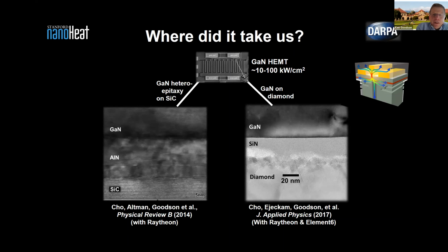It's basically a power transistor that's used for radar applications, a lot in flight, aircraft, and various things. And it is one of the great power density challenges of our day, because it's delivering millimeter wave signals, and the better you cool the device, the greater power density that you can emit. And the GaN provides great mobility and other electrical features, but the problem is that it's not a very good heat conductor. So typically it's bonded to silicon carbide, or in a very innovative approach, bonded to diamond. Diamond is the best heat conductor at room temperature, and the bonding then provides you a good heat conducting substrate below the functional gallium nitride.